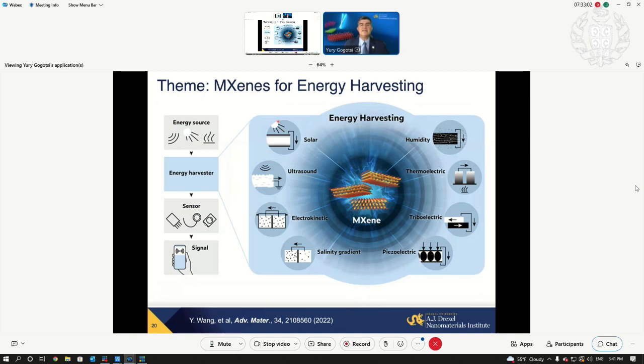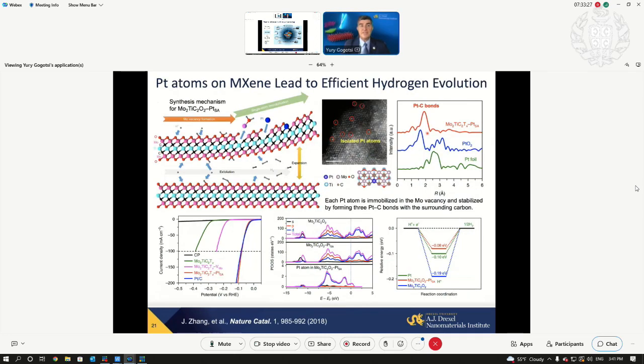And naturally, they are already being explored in solar energy applications, particularly as electron and hole transport layers in solar cells. They can harvest ultrasonic, electrokinetic energy, salinity gradient, piezoelectric, triboelectric, thermoelectric, humidity energy, and so on. So there are many ways they can be used in energy harvesting. We showed that by incorporating single platinum atoms in defects, vacancies on the surface of MXenes, we can achieve the same performance as the conventional platinum-on-carbon catalyst used for the hydrogen evolution reaction, for hydrogen production, but with at least an order of magnitude smaller use of the noble metal, platinum.